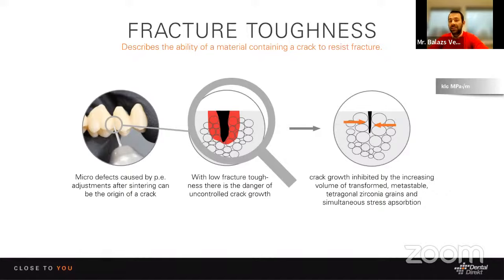But the cracks, even though you don't see them, will still be there, and with time they will increase if there are any, and maybe just a year later or half a year later, you will have a problem with the crowns. And this is what makes our material so outstanding, because of that metastable tetragonal phase, and because of that crack stopping property, the fracture toughness.